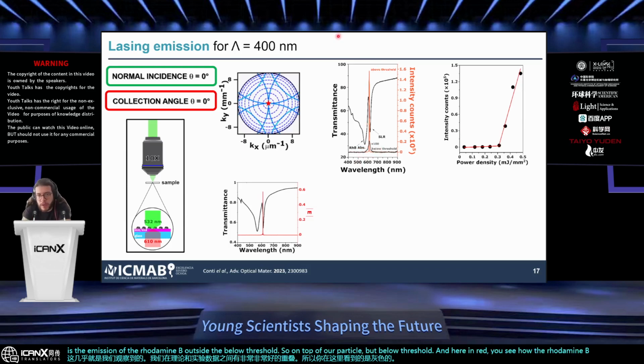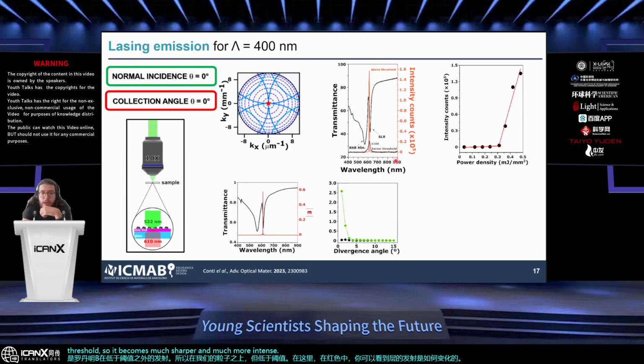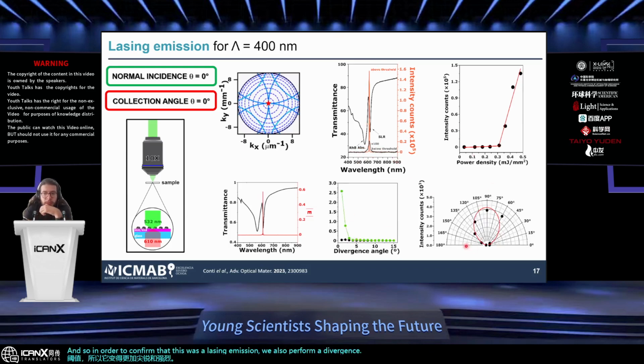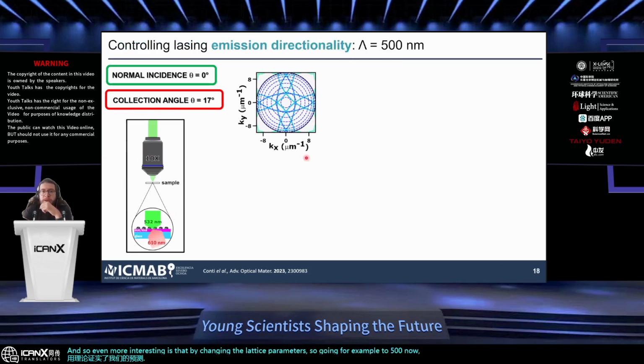emission of the layer changes above threshold, so it becomes much sharper and much more intense. And so in order to confirm that this was a lasing emission, we also performed a divergence and a polarization study, confirming what we predicted by theory. And so even more interesting is that by changing the lattice parameter, going, for example, to 500 nanometers, in this case we do not expect the lasing emission to come out straight at normal incidence, but actually we expect it at a slight angle.